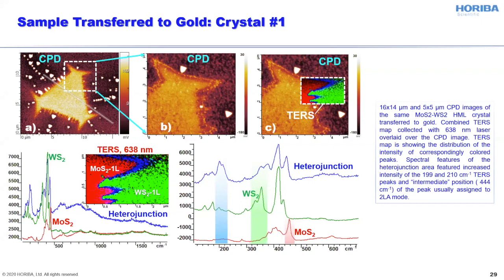And more importantly, the width of the transition area between the molybdenum disulfide and tungsten disulfide is not uniform. You can see that, for example, here, the width of this transition area is a few hundreds of nanometers, while in this area the width is, as we will see further down the presentation, pixel limited, so at least 25 nanometers or probably less.